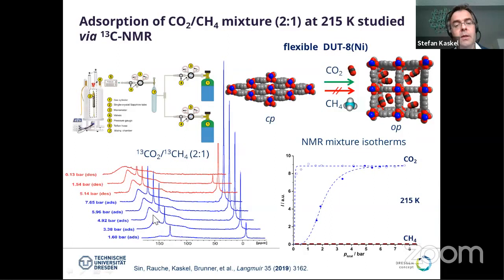And this broad signal is getting stronger and stronger. Here you see the adsorbed CO2 getting stronger and stronger. And then once we desorb it, it's lost again at a certain point. This allows you to integrate the signal and to measure the adsorption of CO2 in situ with NMR spectroscopy.